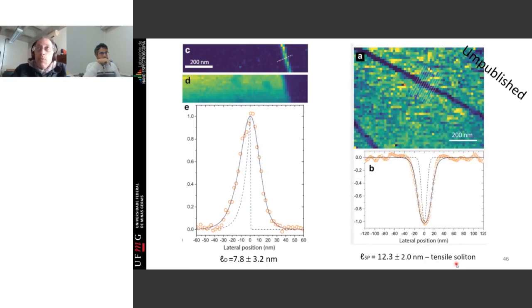And I can do the same with the strain soliton. So here's the soliton of strain. Here are the AB and BA areas. And if I now do the deconvolution of the donut illumination, I see that the soliton of strain is 12 nanometers wide, okay? And when you look at the STM image, this is exactly what you get.